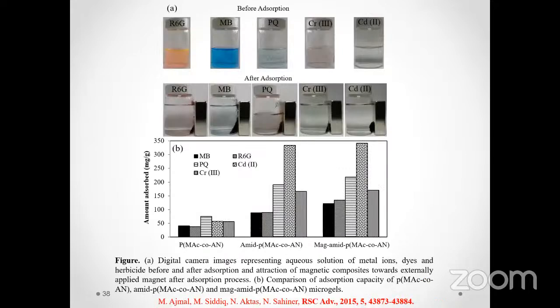So here is the advantage of using magnetic behavior, or using the magnetic nanoparticle for the formation of these composites with hydrogels, that once the dye, or once a pollutant has been adsorbed on the hydrogel system, then you apply an external magnetic field. The adsorbent containing the contamination is attracted towards the externally applied magnetic field, and you can simply decant the water which has been now purified.